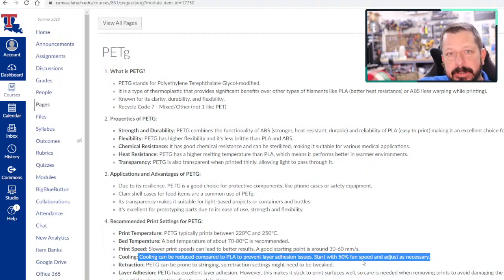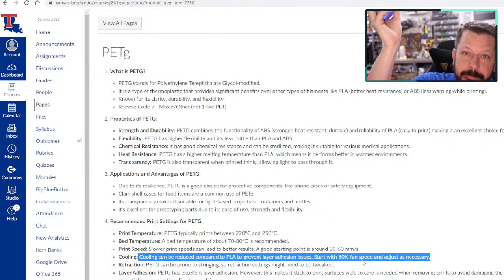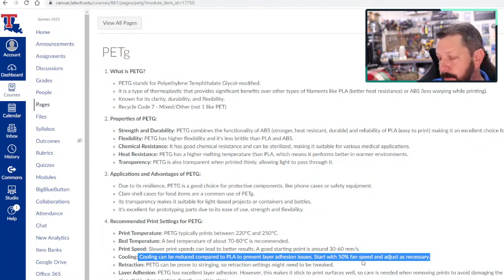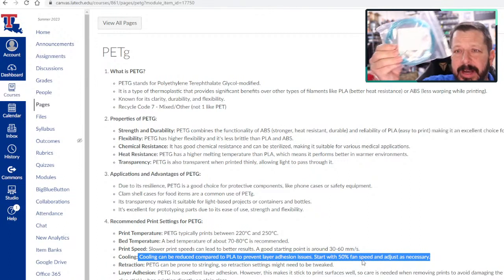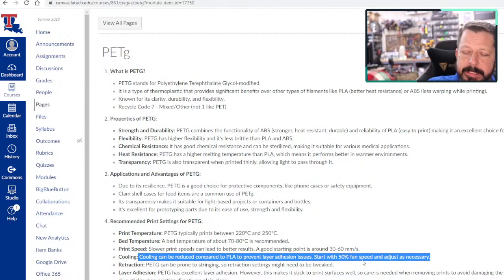Normally with PETG, you don't want a lot of cooling because it will do the same thing that our vase here did. No matter what your flow rate or temperature is, it will delaminate because it doesn't adhere too well to the prior layers if you have a lot of part cooling on it. But if you have no part cooling, it gets really stringy. So your part just doesn't have as nice a surface finish, and it's got strings everywhere. So I usually run PETG with 50% layer cooling. I don't know if I'll try this one with 100%, but I'd suspect it's going to have weak layers. But that's what it says on here, so I don't know.